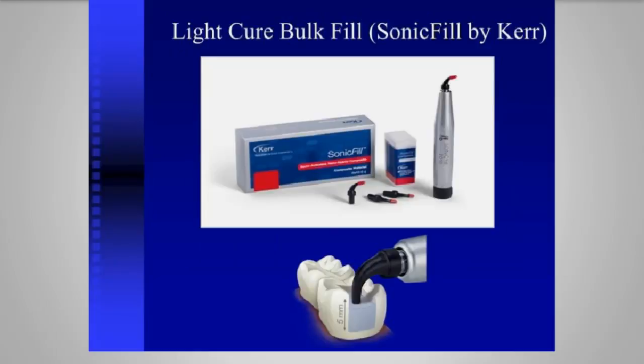What are some of the products on the market? Let's talk about one a lot of my colleagues use, and this is SonicFill from Kerr. For disclosure, I have not used this one myself, but I've heard a lot of good things, and their claim is you can bulk fill it up to 5 millimeters. And the Sonic handpiece here is about $850, and by vibrating the material, it changes the viscosity up to 80% to make it more flowable.